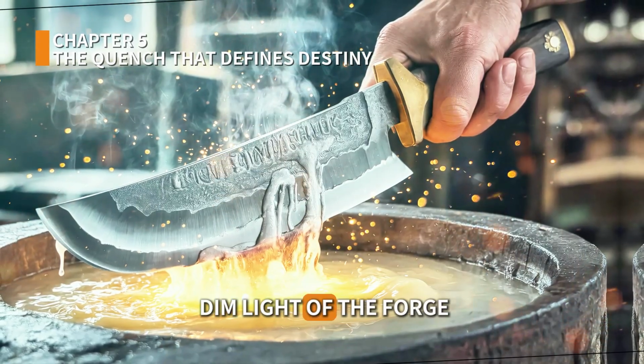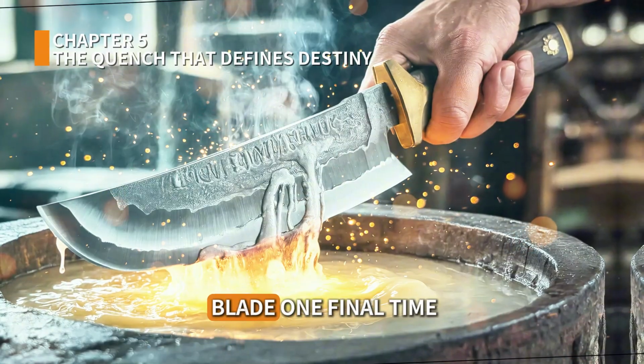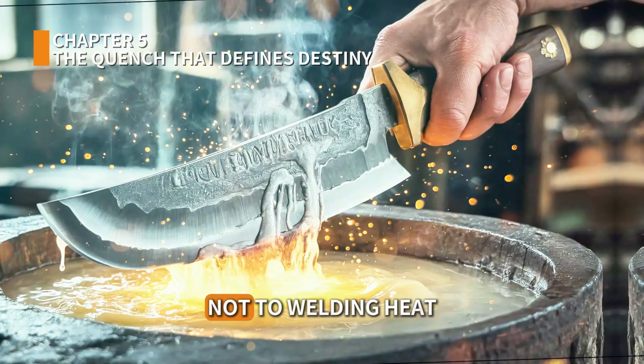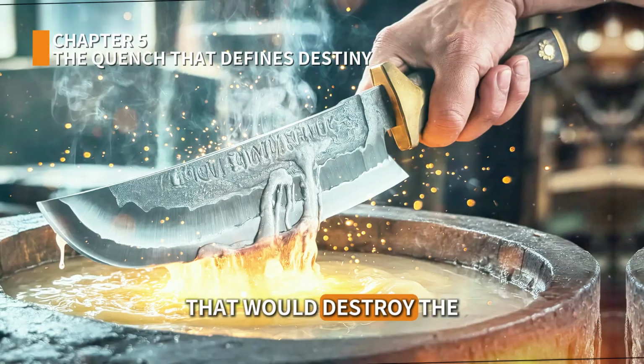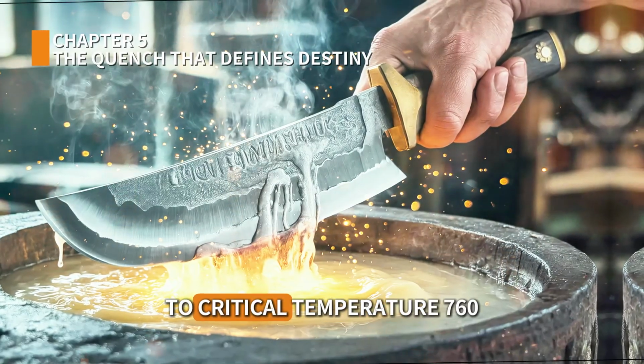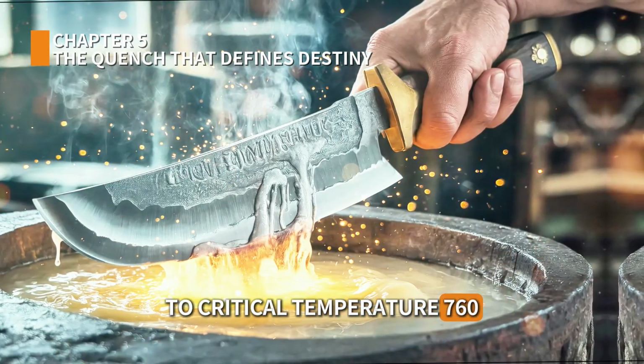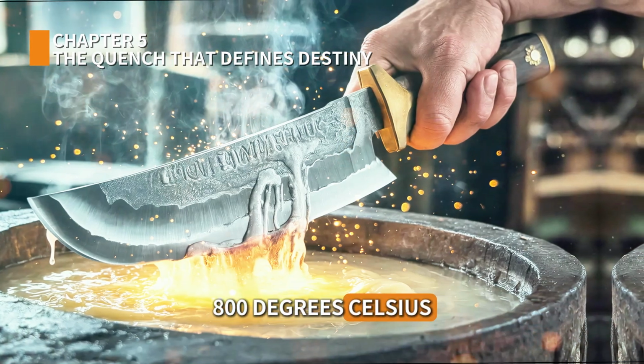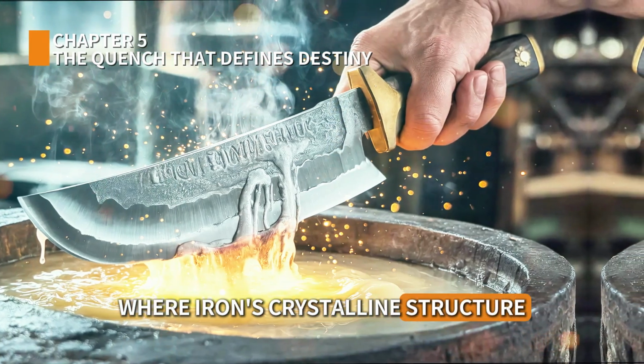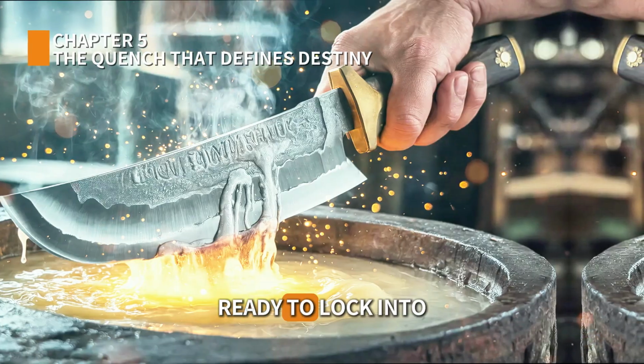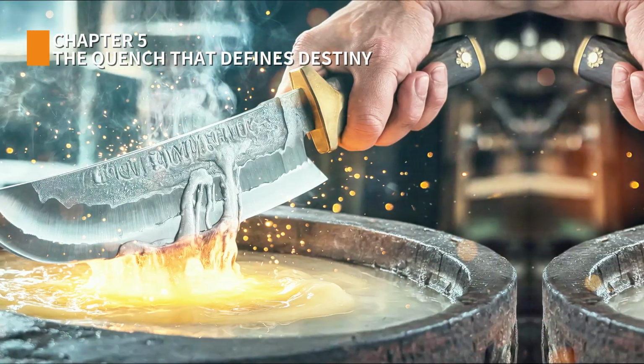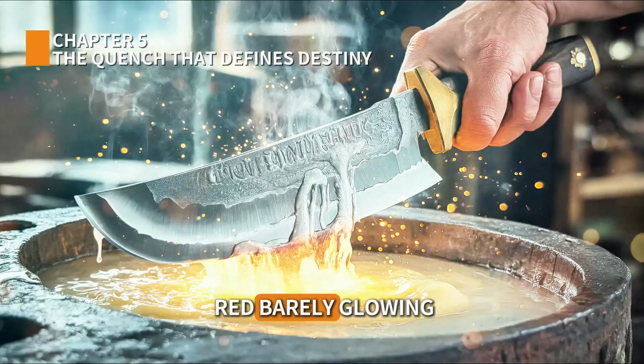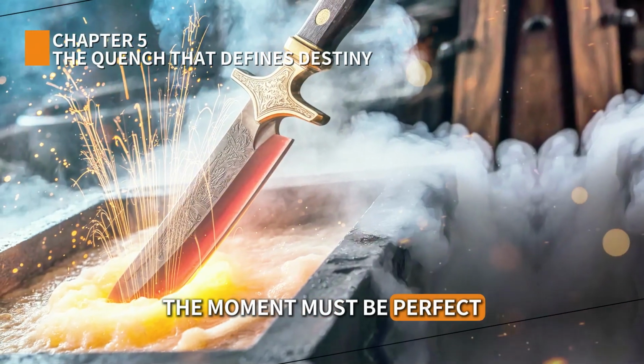In the dim light of the forge, the smith heats the blade one final time, not to welding heat that would destroy the careful layering, but to critical temperature, 760 degrees Celsius, where iron's crystalline structure becomes fluid, ready to lock into new configurations. The color is deep red, barely glowing. The moment must be perfect.